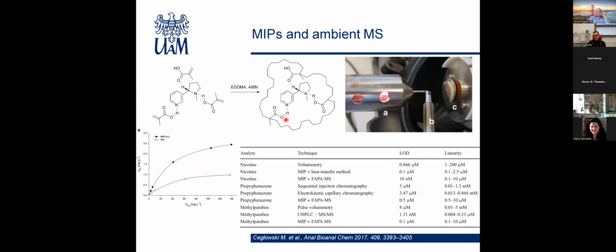And that was the time when I started working with molecularly imprinted polymers, MIPs. Initially I produced the simple MIPs, let's call it, so the one using methacrylic acid and EGDMA, ethylene glycol dimethacrylate, with simple radical polymerization using AIBN. And always when we do MIPs or other adsorbents, we investigate the adsorption isotherms.